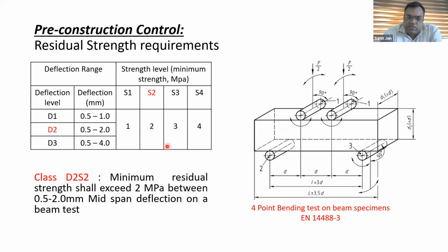Next is the residual strength requirements. The figure shown on the right side is a 4-point bending test. Here the beam specimen is prepared with shotcrete, and then it is tested in the standard apparatus, and the categorization of the class is done by the deflection and the residual strength of the specimen. So these are the categories defined in the European norm: there are 3 deflection levels and 4 strength levels. If we qualify shotcrete to be D2S2, then it should have a minimum residual strength of 2 MPa in the range of 0.5 to 2 mm deflection. The deflection is measured at mid-span of this test.